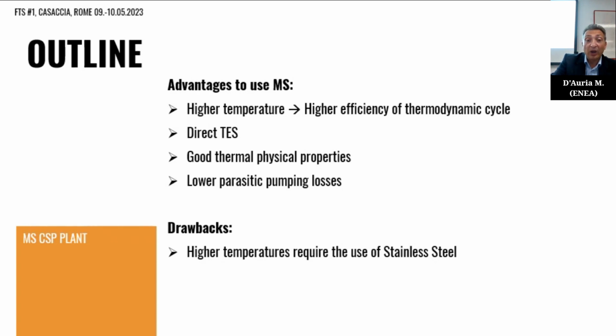However, working at temperatures higher than 400 degrees with the current molten salt requires the use of stainless steel in piping, vessels, and other elements, since the corrosion issues are well known when carbon steel is used with sodium and potassium nitrates at this temperature.